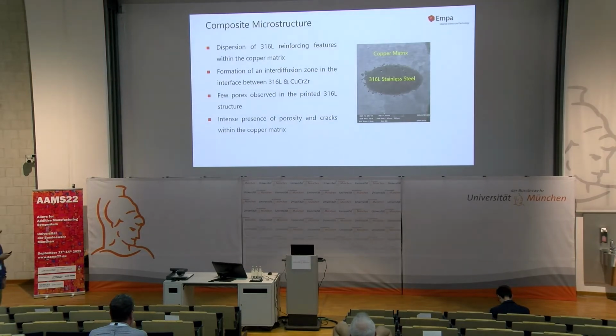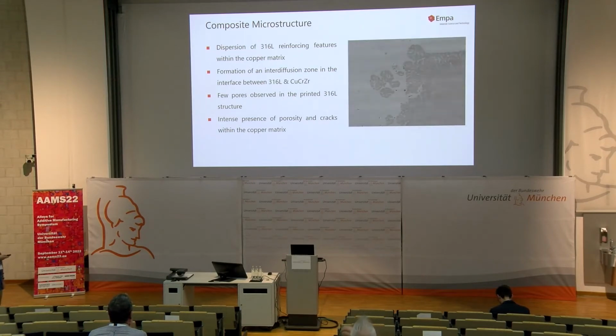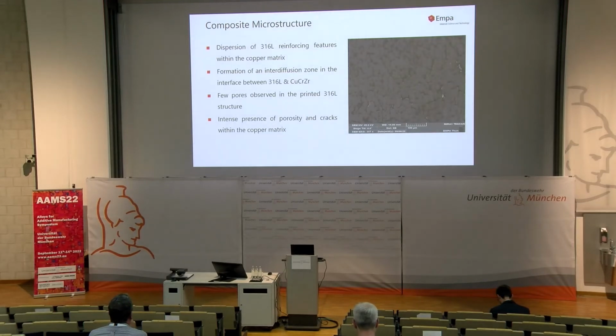So, from the analysis of the microstructure, we can see the copper matrix, inside of which we have these ellipsoids, which are part of the reinforcing structure of 316L stainless steel. And by having a look on the interface between the steel and the copper, we see this characteristic layer, the width of which is around 50 micrometers, with this island-shaped structure, which is a first sign of good metallurgy, the creation of an interdiffusion zone between the different alloys. What we saw from the steel part is that we do have the appearance of some small pores, but the porosity problem is more intense on the copper part. This is something that we're going to discuss more analytically later.